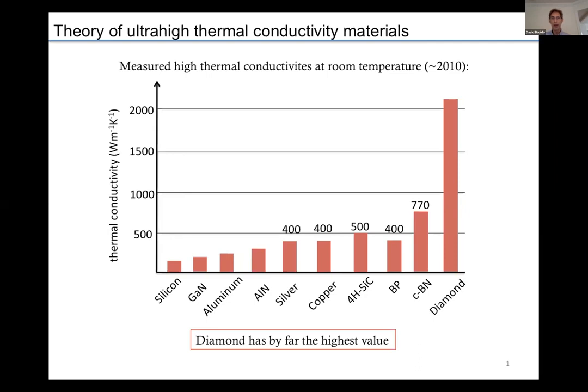And what really stands out in the plot is that diamond's thermal conductivity is by far the highest, considerably higher than some of the other materials that you saw on some of Bara's charts involving, say, copper and aluminum. Diamond is an electrical insulator. The best metals, copper and silver, have 5 times lower thermal conductivity. So we want to see what we can learn about why diamond's thermal conductivity is so high, and are there other materials that can approach its high thermal conductivity. And of particular interest to us, which I'll come back to later, are the 2 boron compounds, boron phosphide and cubic boron nitride. So I'll talk about those at the end of my talk.